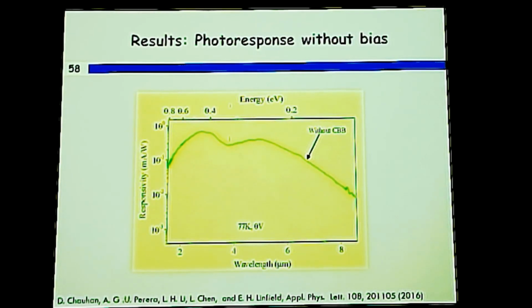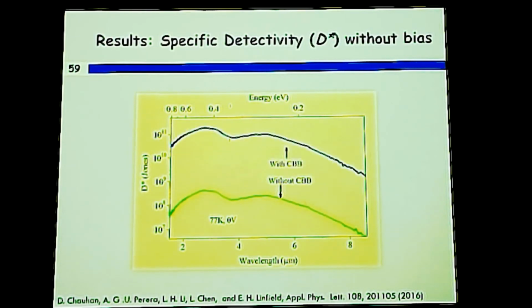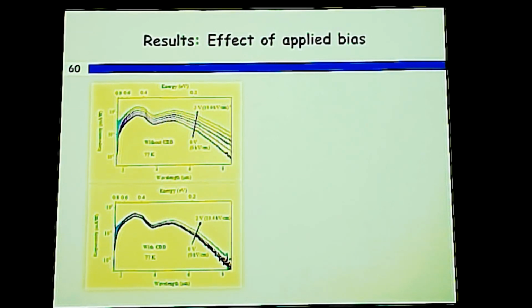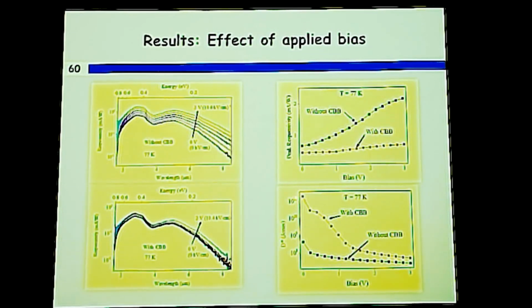The photoresponse with the current blocking barrier was slightly weaker compared to without the current blocking barrier. However, the specific detectivity, D star, was much higher, about 2 orders of magnitude higher with the blocking barrier, and that operated at 0 bias because of the graded barrier. With the application of bias, the photoresponse increased slightly in both cases. However, the specific detectivity decreased with the bias, because with the application of bias, the dark current increases significantly, and that causes the specific detectivity to go down. So that means with the graded barrier, the 0 bias operation appears to be the most optimized condition for the operation.